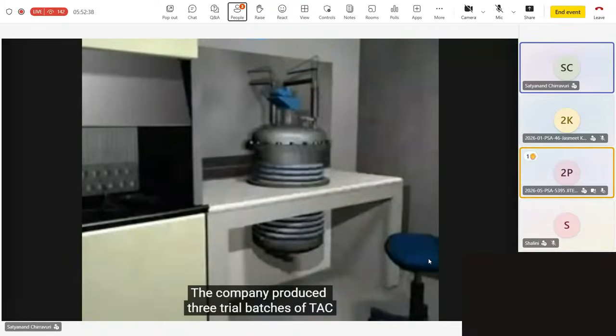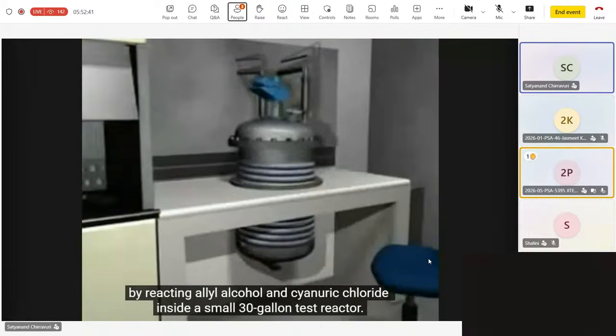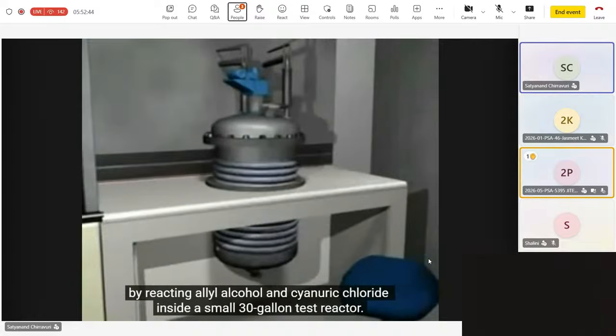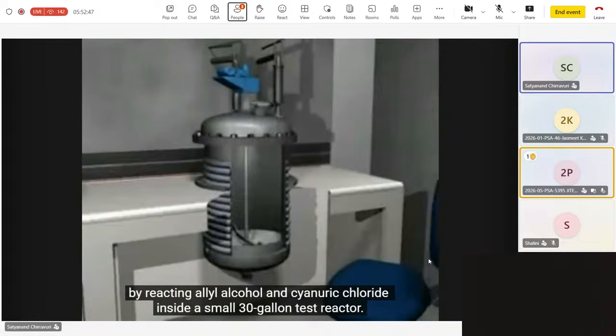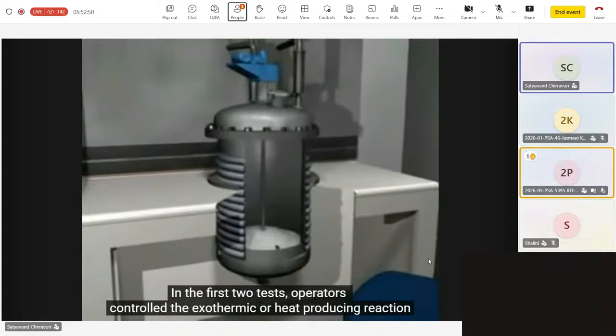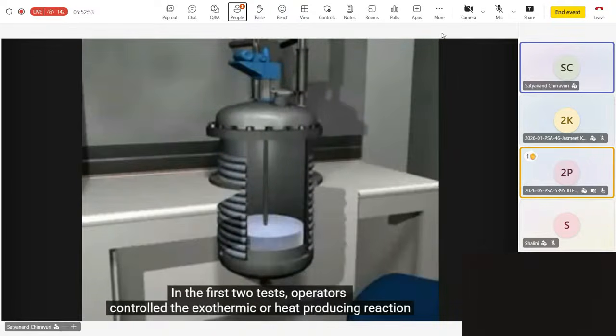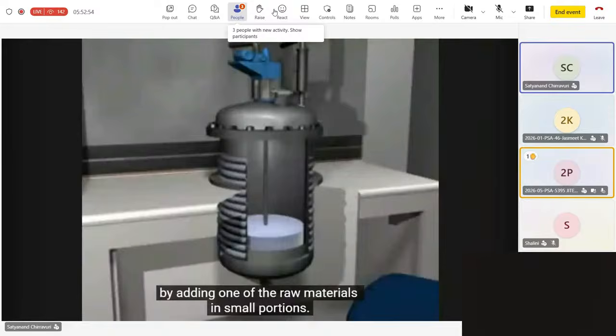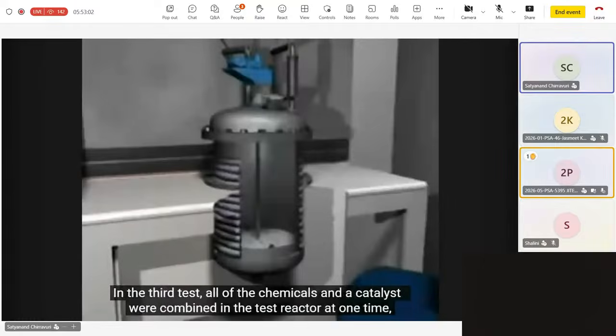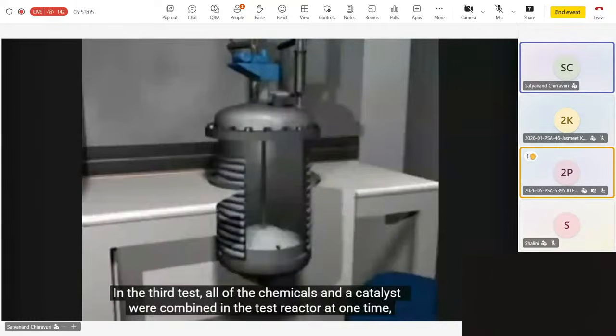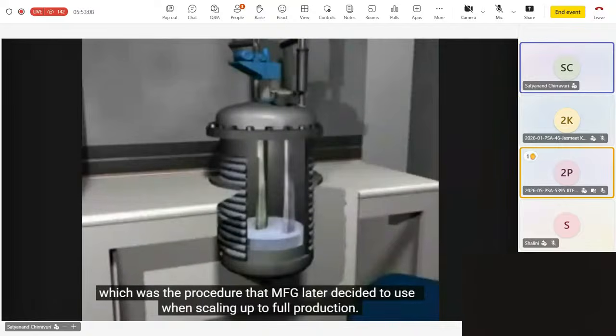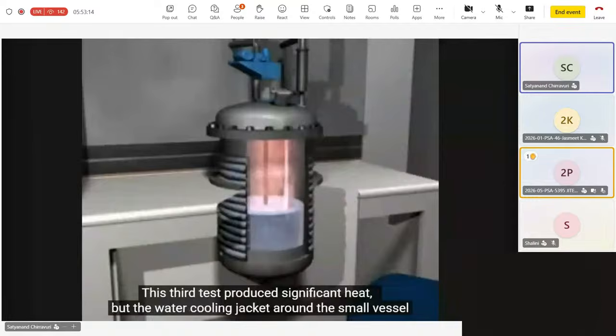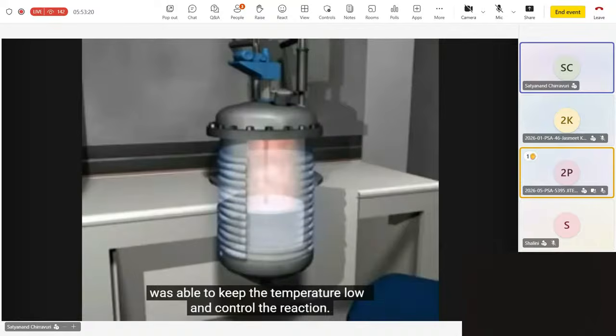The company produced 3 trial batches of TAC by reacting allyl alcohol and cyanuric chloride inside a small 30-gallon test reactor. In the first 2 tests, operators controlled the exothermic, or heat-producing, reaction by adding one of the raw materials in small portions. In the third test, all of the chemicals and a catalyst were combined in the test reactor at one time, which was the procedure that MFG later decided to use when scaling up to full production. This third test produced significant heat, but the water cooling jacket around the small vessel was able to keep the temperature low and control the reaction.